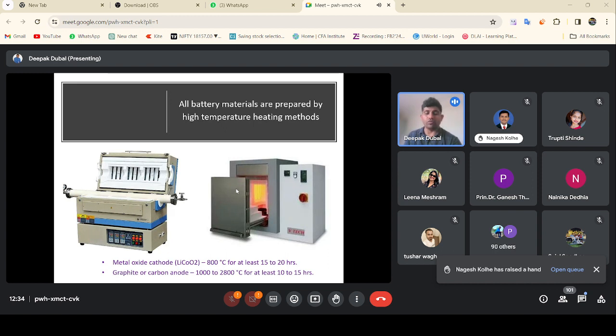So you can see here, if I want to synthesize the lithium cobalt oxide material, it needs almost 800 degrees Celsius, because most of these battery materials have a particular crystal structure, mostly a spinel structure, olivine type structure, or layered crystal structure. These structures only form at a very high temperature, over 600 to 700 degrees. So if I want to synthesize any cathode material for batteries, we have to go over 800 degrees. And the reaction is so long, 15 to 20 hours of reaction.